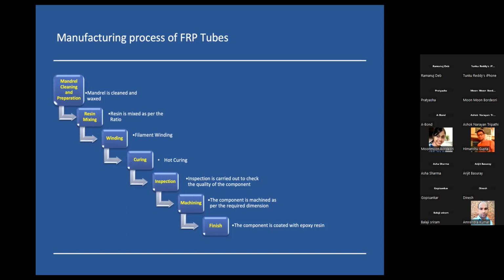After the filament winding process is done, the mandrel on the machine itself is post-cured to a certain temperature for a certain duration of time. The post-curing process is very essential, because that only will retain the mechanical and electrical properties of the component. After the post-curing is done, we take the mandrel with the cylinder and put it in a chamber in an oven for further post-curing, and after that we extract the cylinder from the mandrel.